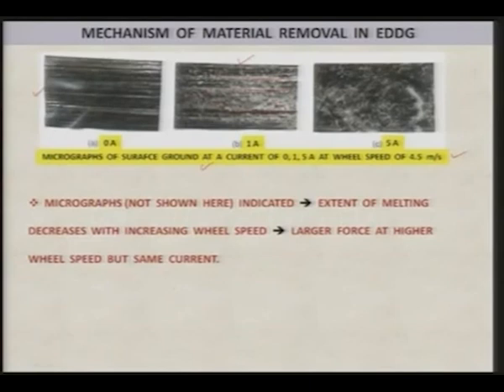Now, if you go for the third micrograph, where 5 ampere current is being supplied between the grinding wheel and the workpiece, there are only 1 or 2 grinding marks clearly visible. Otherwise, the rest of it is clearly visible craters of different sizes, as you can see I have marked some of them over here. So, this indicates that the major removal of material at 5 ampere is due to the EDM process. However, grinding is also contributing substantially, but it is not visible because the frequency of sparking is quite high,